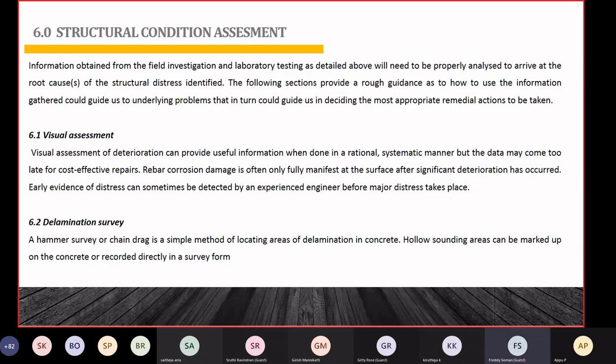Because from the crack pattern, where the crack appeared, and at what age it appeared, we get a lot of clues to find out the root cause of the deterioration, particularly for cracks. That's why crack patterns are very important, and whenever we go for any investigation, we want to incorporate this type of visual assessment as well.